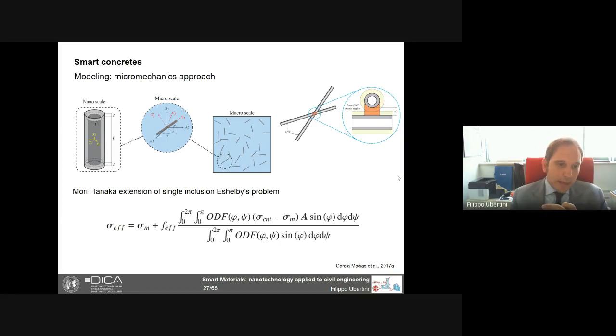So for instance, we can predict, as in the equation you see in this slide, the conductivity tensor of the composite as a weighted average. Let me take this easy way of saying things, a sort of weighted average between the conductivity tensor of the matrix and the conductivity tensor of the nanotubes. Of course, the weighting is based on the effective volume fraction of nanotubes, because we are considering the interface between the nanotube and the matrix.